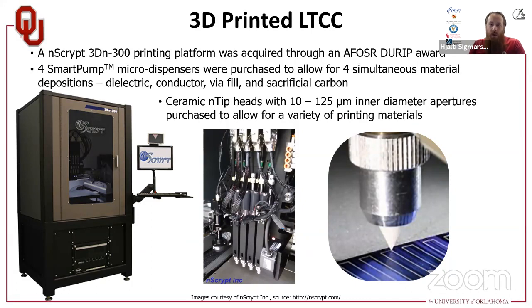But in general, what we wanted to do is be able to put down 4 suspensions at the same time, so that we can do our substrates with our dielectrics, we can do our connections, and we actually use a different conductor for the via fill. It needs to have a different sintering performance. So we fill vias in between with different material, and then sacrificial carbon, and I'll show in a little bit why we need that. We also got a variety of these ceramic tips, a whole bunch of them, and we're experimenting with which suspension works best with what inner diameter apertures. These are the kind of things that we're doing.